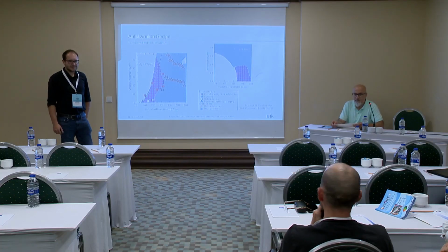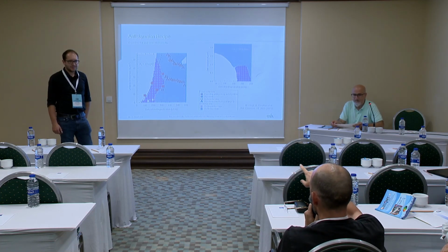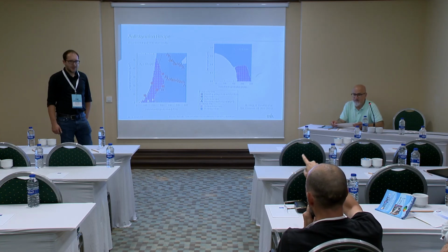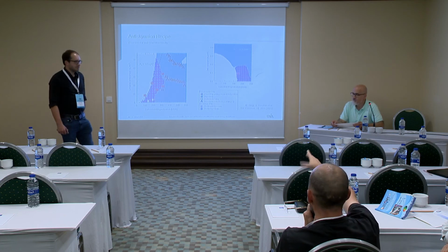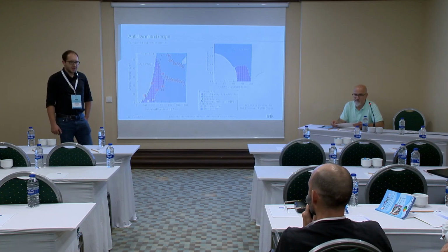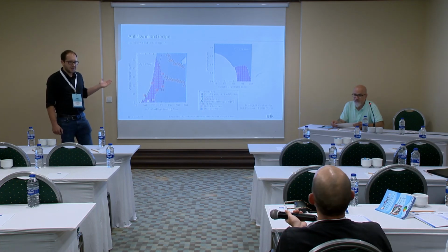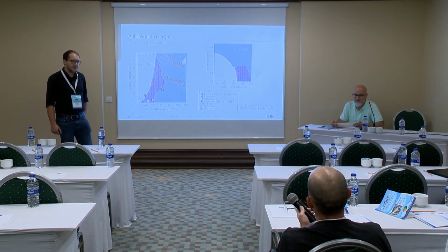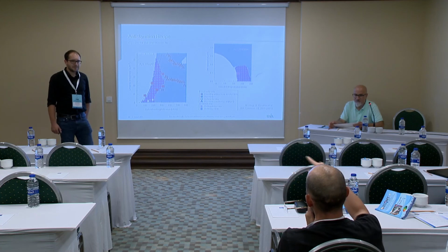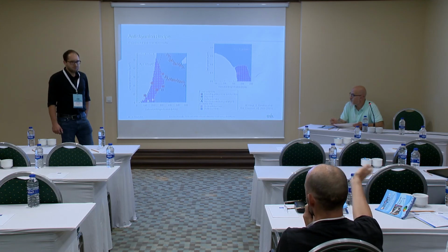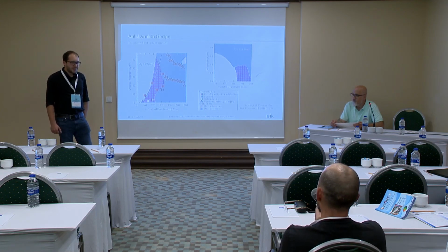Okay, thank you. Maybe related to the same question: are you sure that you can change the saturation magnetization without changing the DMI, and that you get antiskyrmions without DMI? I guess we have such low DMI that it can't be a stabilizing factor, and the dipolar interaction in our films is the main factor for this stabilization, yes. Okay, and then DMI and saturation magnetization here are two independent parameters, or anytime you move one, you move the other? I guess they're fairly independent.